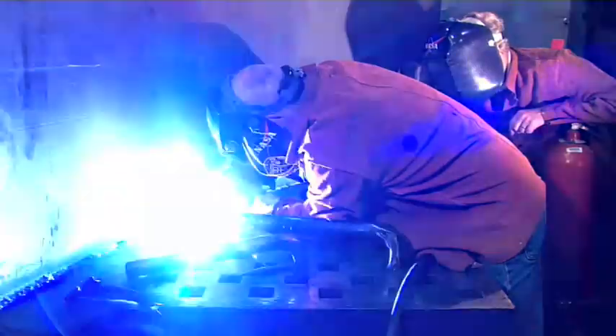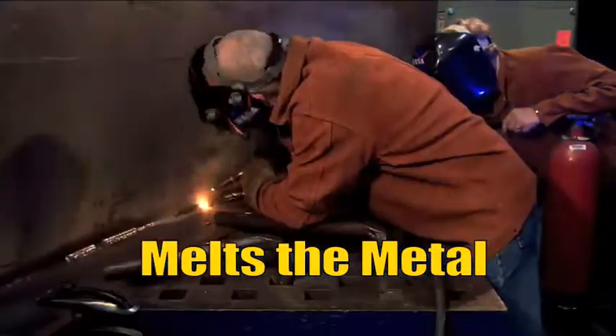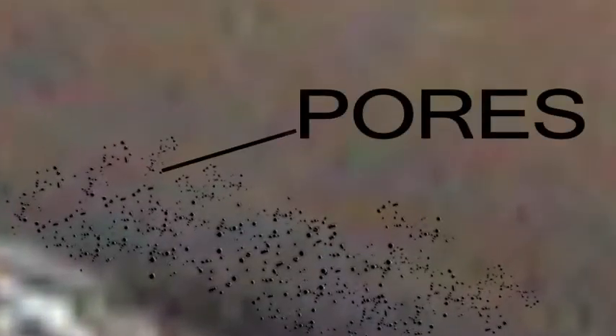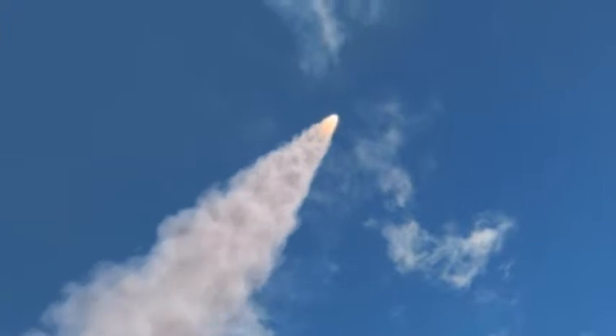But when you weld pieces of this material together using traditional fusion methods that will melt the metal, you get big problems in the form of tiny holes. These small pores weaken the metal and make it useless in an application like Ares-1. So NASA needed to find a better way to do it.